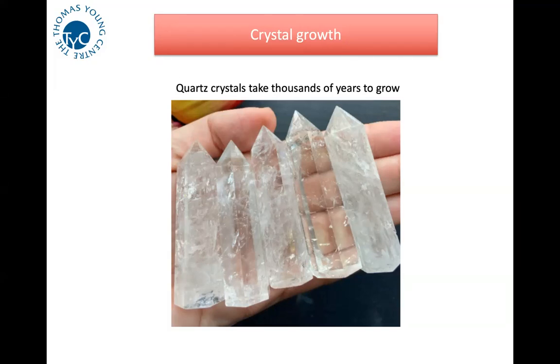Particularly if it's not a metal. In a metal, the energies between different crystallographic orientations are less, but nevertheless you can get faceted metal crystals by a natural minimization of the free energy. And of course, if you have a free standing theoretical crystal, the minimum free energy shape is called the Wulff shape, where the facets are adjusted so that they obey the Wulff construction, and that tells you that the distance of the facet from the center is proportional to its surface free energy.